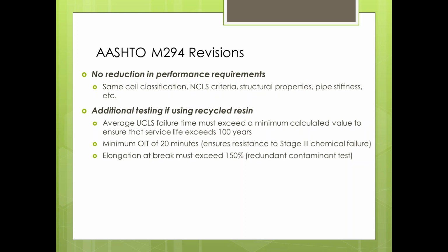of 20 minutes. That limit was really set there based on a lot of research from the gas pipe industry and others that have done extensive testing on what type of antioxidants and what volume of antioxidant packaging is required to prevent that chemical or oxidative failure. And in addition, there is an increase in a redundant contaminant test in the elongation at break test, which is basically where they do this typically for typical tensile testing and ductile testing for even virgin resins, but they'll be taking those samples and it cannot break before exceeding 150% elongation in those wishbone samples.